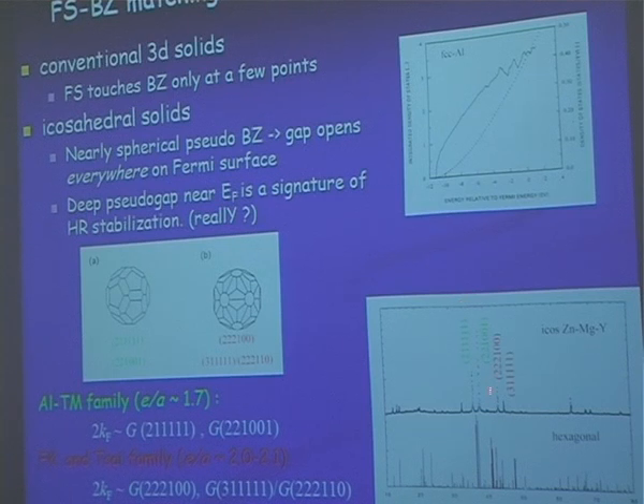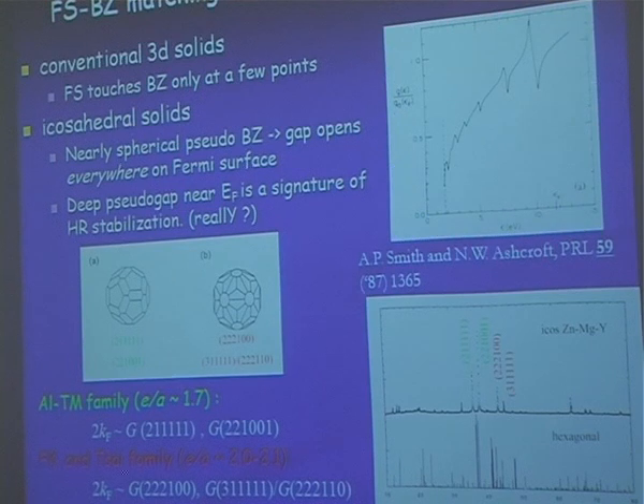And we have other diffraction peaks at a little bit larger wave vectors here. By constructing the Brillouin zone with the bisecting planes of these wave vectors, we have such a nearly spherical Brillouin zone. So if the Brillouin zone is nearly spherical and the Fermi sphere touches it, a gap will open everywhere on the Fermi surface. So that means we have larger peaks and dips and a gain of the boundary energy.